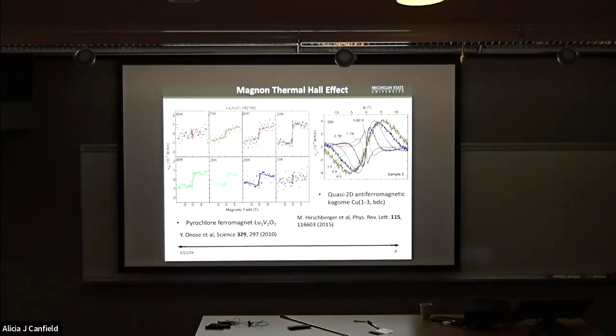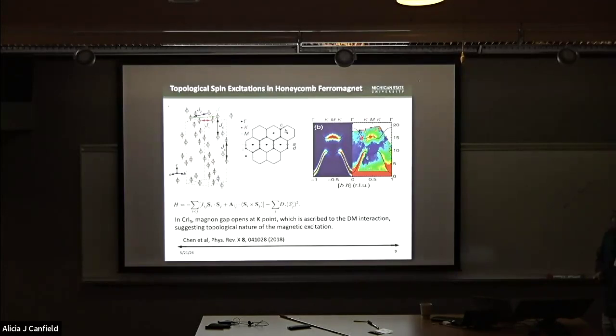About 6 years ago, there was an inelastic neutron scattering study on chromium triiodide, where chromium occupies the honeycomb lattice.